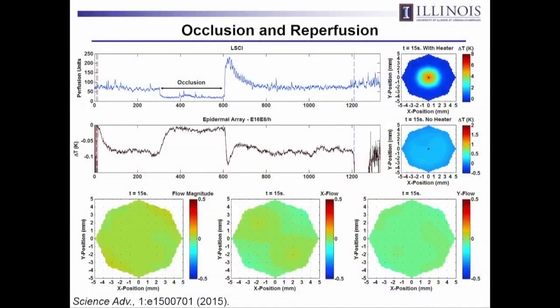And it turns out that you can correlate that measurement to the clinical gold standard, which in this case happens to be a laser Doppler-based technique, super sensitive to vibration, motion artifacts, certainly not wearable, but that is the gold standard. And so what we did is we mounted one of the devices on the forearm, and then we could occlude the radial artery to shut off blood flow, and then we can measure the dynamics of how that occlusion leads to rapid decrease of blood flow measured by the laser technique. And then when you release the occlusion, the blood flow rate overshoots the steady state value and then decays back down. And you can measure that thermally with this epidermal patch, and you can see it here.